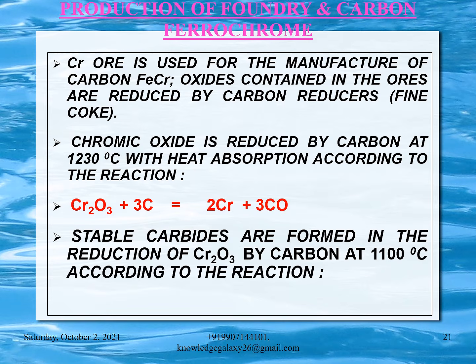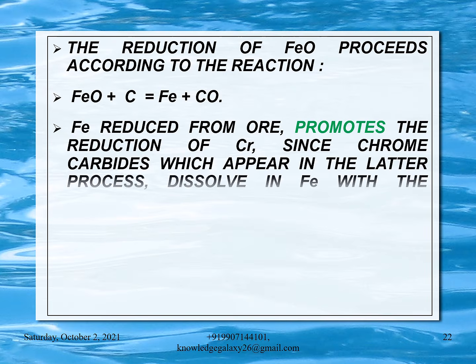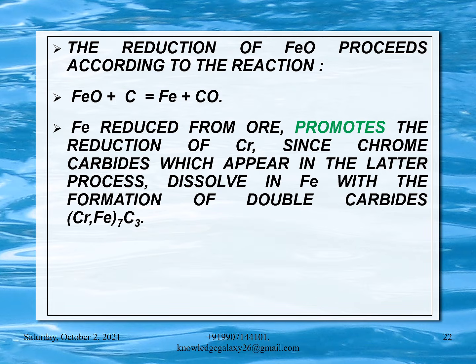Stable carbides are formed in the reduction of Cr2O3 by carbon at 1100 degrees Celsius according to the reaction Cr2O3 + 27/7 C = 2/7 Cr7C3 + 3CO. The reduction of FeO proceeds according to the reaction FeO + C = Fe + CO. Iron reduced from ore promotes the reduction of chromium since chrome carbides which appear in the later processes dissolve in iron with the formation of double carbides (Cr,Fe)7C3.